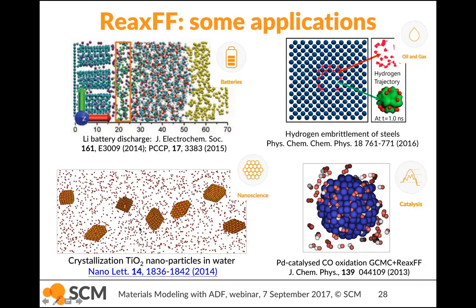If you do that in vacuum, actually you start just forming patched structures, and you don't actually start forming a nanocrystalline material. So in this paper, they were able to show that through the aqueous environment, the nanoparticles have a little bit more interaction with the environment, and they don't stick immediately to where they meet each other. So they have time to realign and start forming the best crystal facet direction for forming larger nanoparticles.